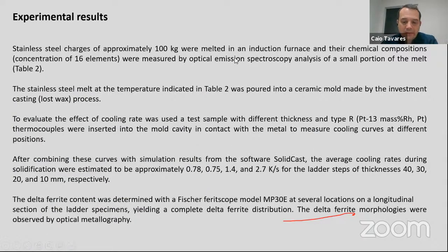So what we did in this work, the intention was to evaluate the effect of the chemical composition of the alloys and the cooling rate of the alloys on the microstructure of the stainless steels. So we made stainless steel charges of approximately 100 kilos, and we checked the chemical composition of 16 elements. In total, we made 16 different heats, and this stainless steel was melted at a given temperature and poured in a ceramic mold that was made by investment casting.